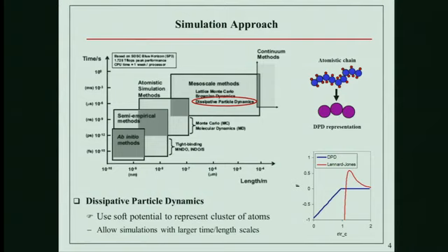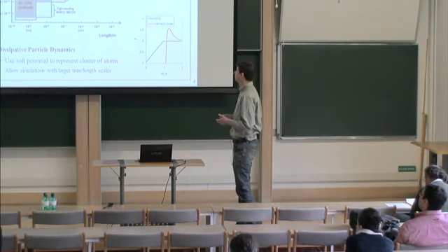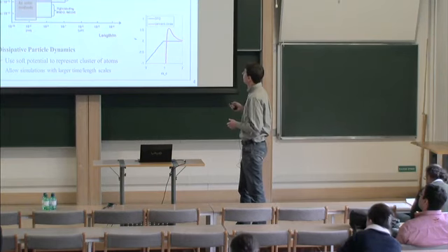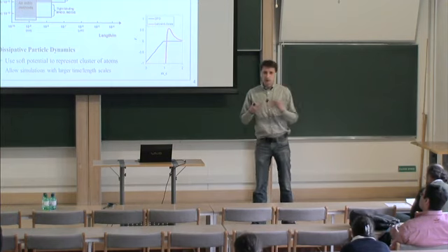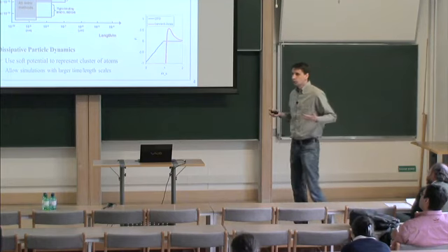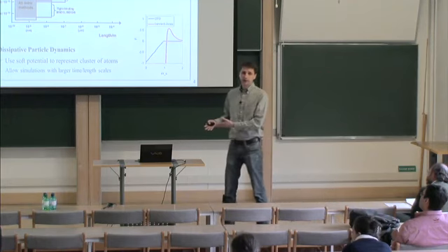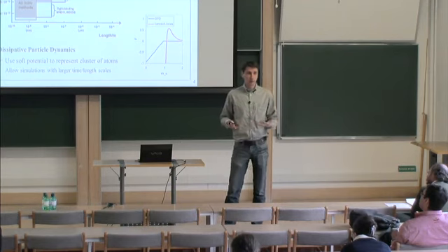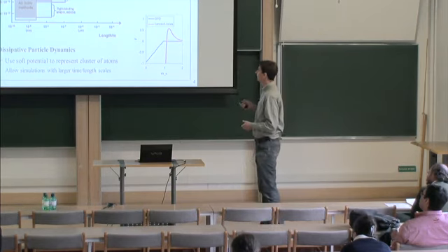In atomistic methods, we should model everything, all the interactions we have in the system, but in that case, we're very limited in the size and time scale we can essentially simulate, even using today's fast computers, supercomputers. On the other hand, if we use continuum methods, we need to have some assumptions about transport coefficients in the system, which apparently depend on this internal structure, and we don't know them. Right, so we are in between.